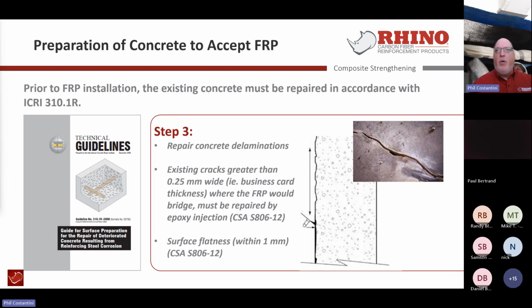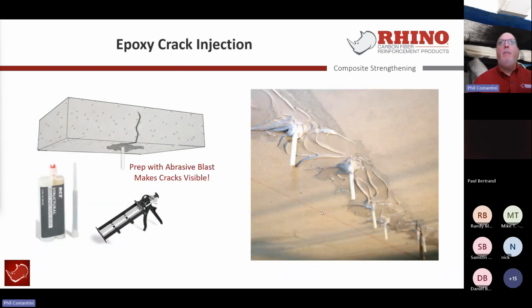But again, to reinforce and add strength in an added load scenario, we have to make sure that cracks are repaired. Well, how are they repaired? Well, there's a variety of methodologies. After the concrete's been prepped with an abrasive blast, so we can make the cracks visible, we have an epoxy crack injection kit or crack injection that should be utilized to bond and reestablish what I call the glue line. It's not good enough just to put a piece of carbon fiber over top of a crack or in a stitching environment. The crack has to be taken care of, especially if it's a through crack on an underside of a slab or in a wall.